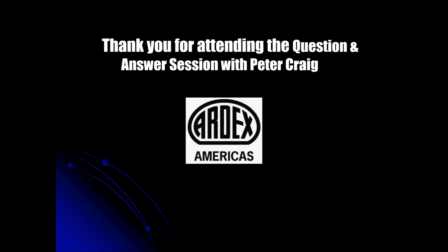Great. And then can a concrete substrate be within appropriate RH values, but be extremely high on the pH scale, therefore creating a hot slab? Well, we are currently at ASTM doing our best to get rid of pre-installation pH testing because the method that has been used for decades is flawed. And the reason it's flawed is because the way it's described in a document that's not even a test method, F710, is to apply a 1-inch puddle of distilled or deionized water, let it sit on the surface for 60 seconds, and then run the pH indicator paper through it.